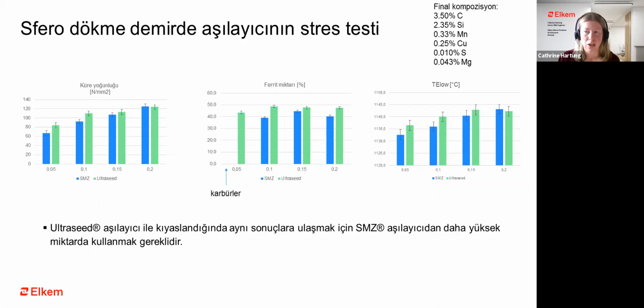You see the same trend with the TElow as you see for the nodule density. So with increasing inoculant addition, your TElow is improving. And here the Ultraseed is also better than SMZ, all the way up to 0.2, where they become more equal. But I should say that SMZ was one of the first inoculants that were developed or patented, but this was originally an inoculant that was developed for high strength gray iron. So it was available when ductile iron was developed or invented, but the inoculant itself is older than ductile iron. So it was there, but it was never really designed to work in ductile iron.